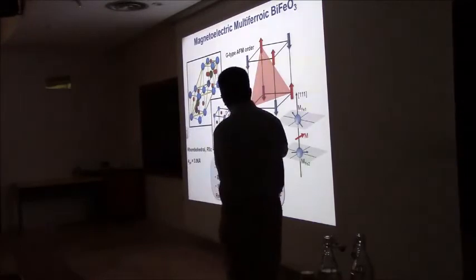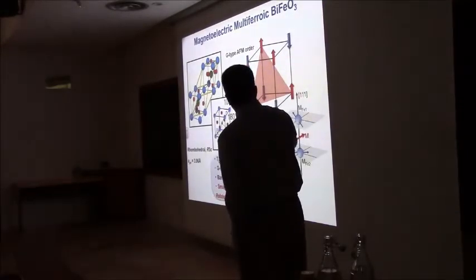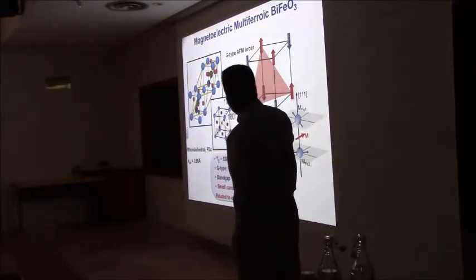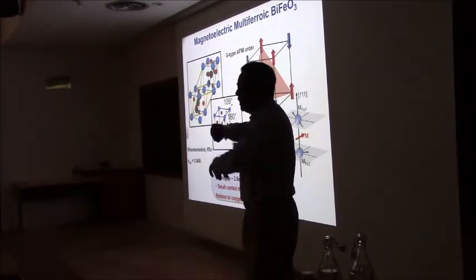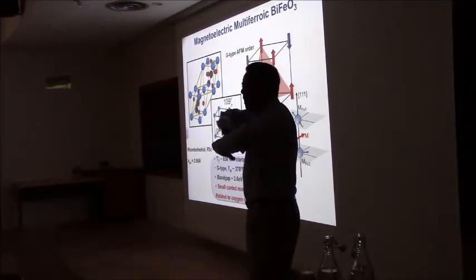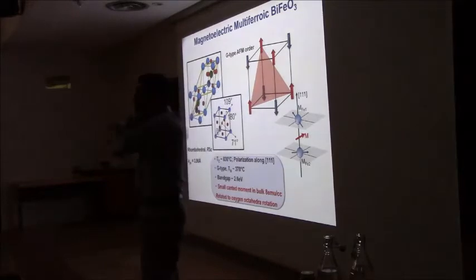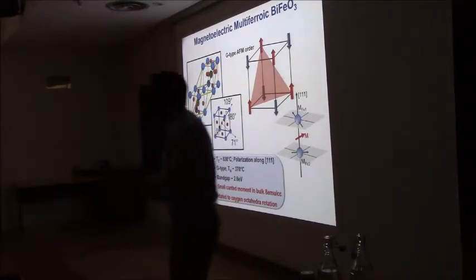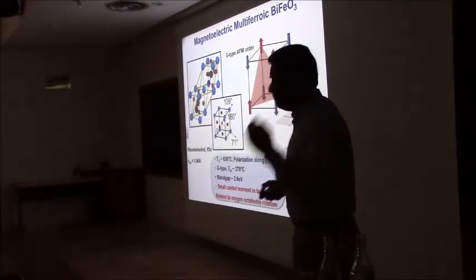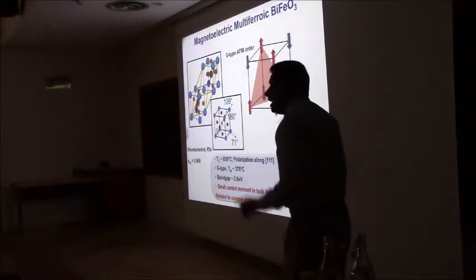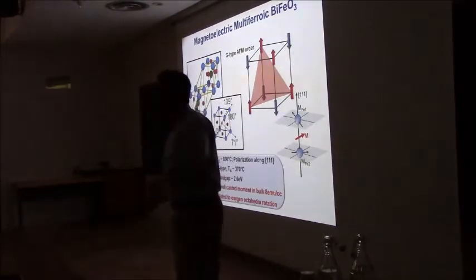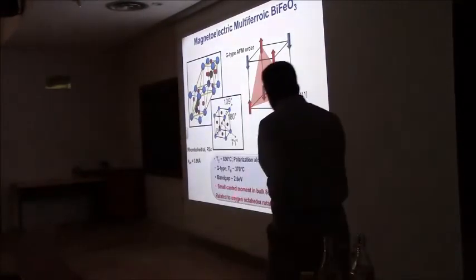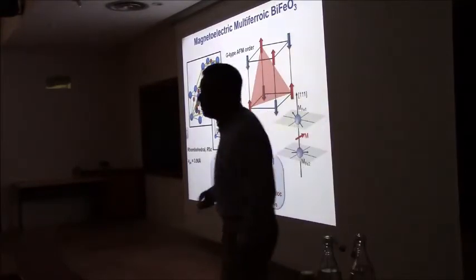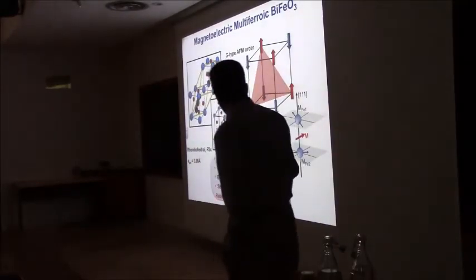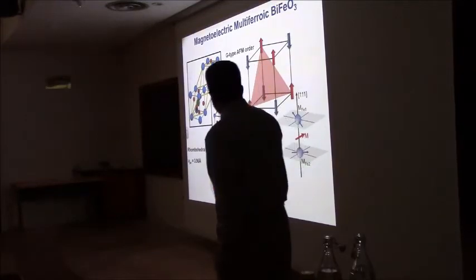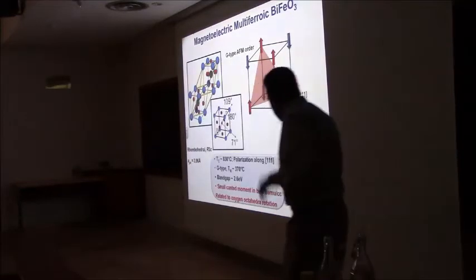G-type antiferromagnet, which you saw already, that's the 111 plane. The spins are ferromagnetic in the plane, antiferromagnetically coupled out of the plane. And because of Dzyaloshinskii-Moriya coupling, there's a small canting. That canting is now becoming very important. That canted moment is a very critical player, as you will see in the next few slides. Band gap 2.6, which means it's very optically active in the visible. Néel temperature very high, of course TC is very high as well.